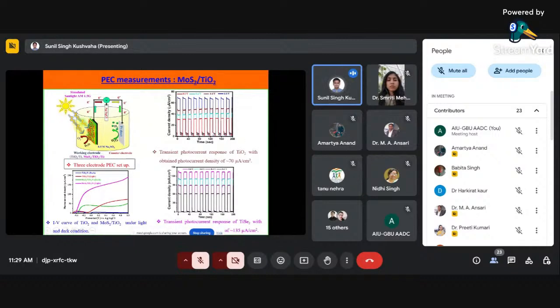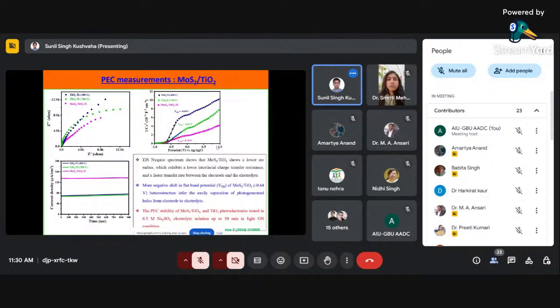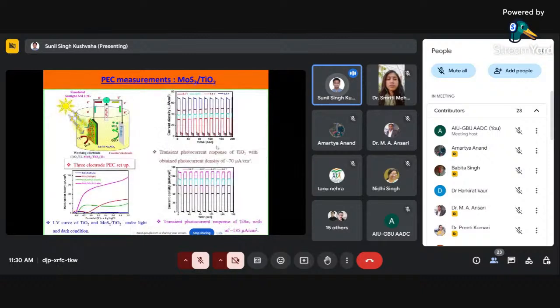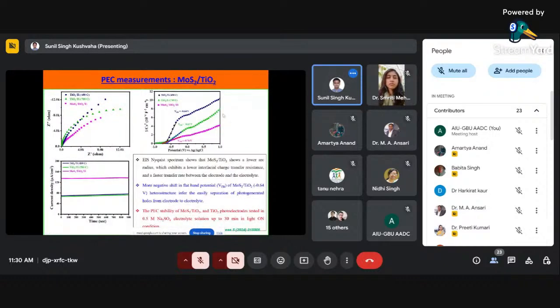When we are doing this with bare TiO2, we can get a photocurrent density of 70 microampere per centimeter square. But after the coating of MoS2, it is showing enhancement. It is almost 2 times enhanced compared to only bare TiO2. And as I mentioned, of course, we have to see the stability test, and after that we have even done different measurements. That is called the EIS Nyquist plot.